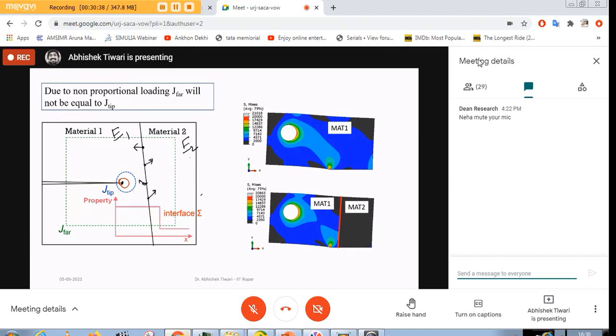Okay, and now let us think. I take the contour here and I take a contour along this green line. Will I get the same value? The answer is no, because in this contour I am having only one singularity, which is the crack tip, and in the other remote contour I have two singularities. I have the interface and I have the crack tip. So in this case J integral is not path independent. And this interface will affect the crack driving force.